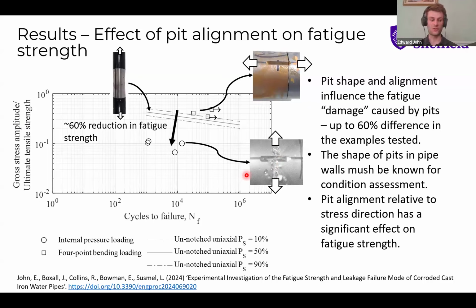So basically this is showing us that the alignment of these pits can have a significant effect on the fatigue strength. So in this case, just knowing the depth of the pit would not be enough to give a good estimate of how damaged the pit is. We'd actually need to understand the shape and alignment of the pit, and also what type of stress the pipe's experiencing, to understand how damaging that pit is.